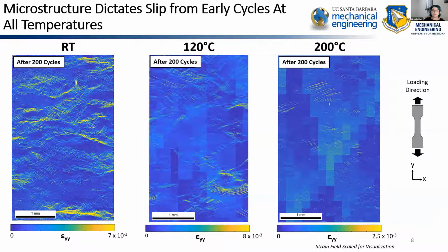And one of the things that we can very clearly see from a comparative standpoint, from the room temperature and 120 C cases where we expect to see a dwell debit versus the 200 C case where we don't expect to see a dwell debit, is that we have significantly more slip activity in the room temperature and 120 C cases than in the 200 C case. And it also accumulated significantly more quickly.